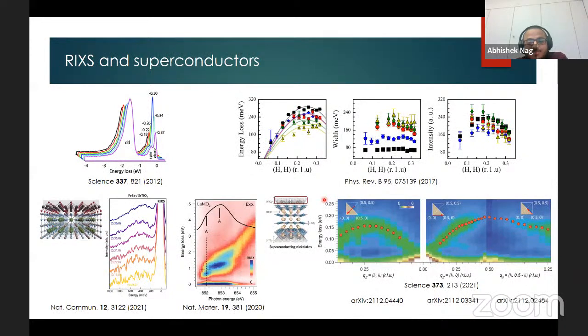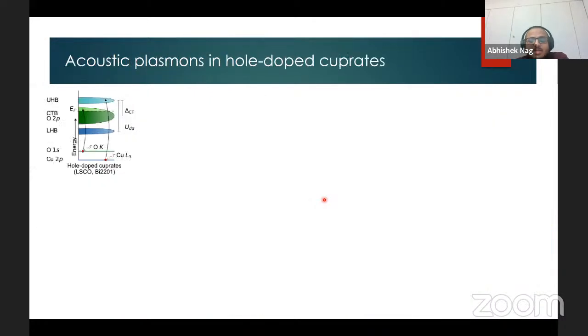Now, coming back to the cuprates, as we have seen in RIXS, we can choose the elements selectively in a system. Since spectroscopically at the copper edge we probe predominantly the upper Hubbard band, and the doped holes in these systems go primarily to the oxygen orbitals, we thought, okay, let's investigate these systems using oxygen K-edge RIXS.